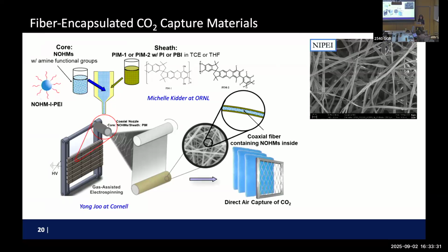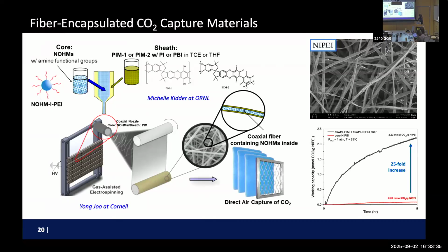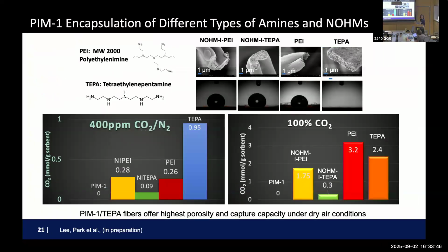It was DOE funding. And these are pictures of some of the fibers. As we expected, this is just the NOHMs, and this is a fiber-encapsulated NOHM capturing CO2 very, very fast. We actually tested many different polymers too. These are two examples. There's PEI, one of the popular amine-based polymers, which is a branched one, compared to TEPA, which has much shorter amine functional groups.